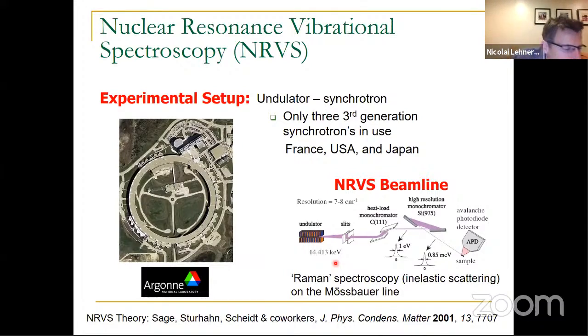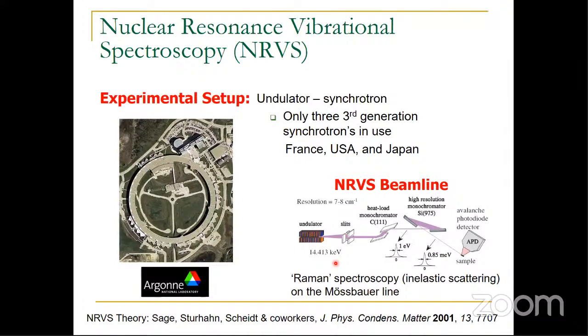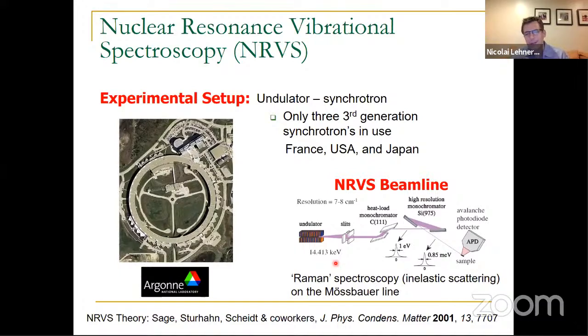And the special thing about this technique is that it has no optical selection rule. That means all the vibrations where iron is moving can be observed. The intensity is proportional to the amount of iron motion, or the square of the amount of iron motion, in your normal mode, right? And there is no other selection rule like in IR or Raman. In IR, you have to have a change of the dipole moment, or in normal Raman spectroscopy, you have to have a change of polarizability. There's no such selection rule here, right? So the only selection rule in that sense is that the iron has to move. So this technique is very good for detecting metal-ligand vibrations in iron complexes.